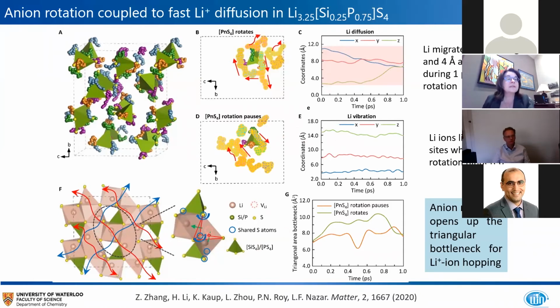As the lithium translates through the lattice, it moves through this little bottleneck, which is a triangular window, and the anion is bound to this edge. So as the anion swings, it opens up this bottleneck, and you can see that that is about a 2 angstrom opening, which is really quite significant. So as it rotates, it opens up the window, and it allows the lithium ions to easily pass through. So this explains the paddle wheel or revolving door concept, and there's more data in our paper that actually shows how the two are coupled.